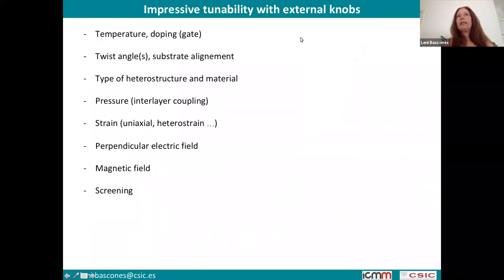Another important thing is the impressive tunability that these systems have. Besides the temperature and the doping that we saw at the beginning, and the twist angle and the substrate alignment that we have seen, or the type of heterostructure, it's possible to play with pressure, with strain, and also with a perpendicular electric field or magnetic field, to tune the bands. So we may have different systems, with different kinds of band structures, but also in this way we can modify the bands more, and in this way we can also modify the phase diagram more. And we can also use screening.